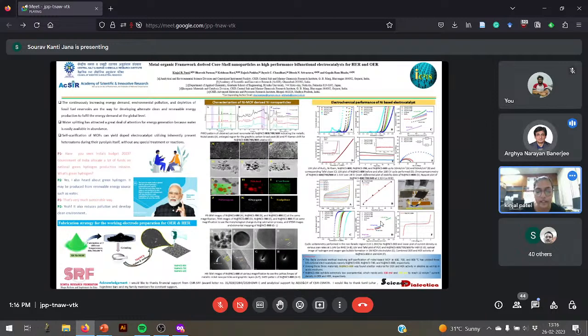Okay. And for the water splitting experiment, what potential or voltage have you used? You have used two cells. Theoretically, water splitting occurs at 1.23 volt. So after that, the overpotential we have measured, using Ag/AgCl here, which also has some potential, 0.197, and the pH also affects it in KOH. So there is 0.059 times pH, which is 13, that we have measured. So pH is 13. Okay. Thank you. Okay, sir.